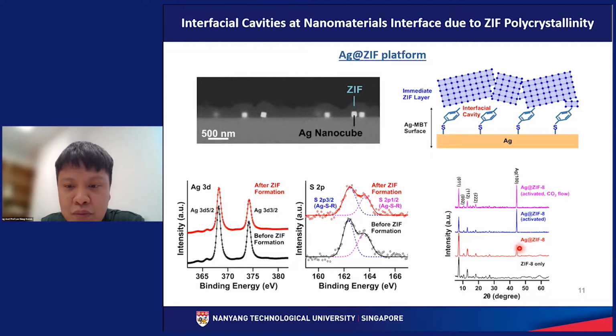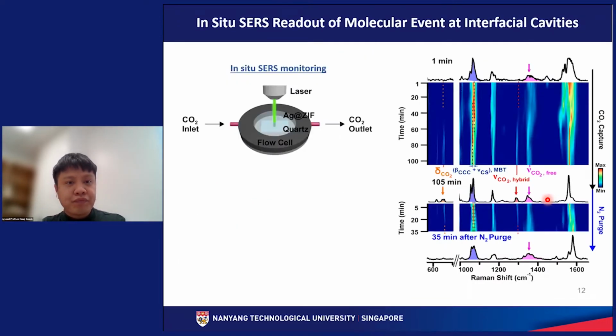Okay, so this MOF layer is very stable, whereby we can activate them under vacuum and high temperature of 120 degrees Celsius, and they can still be around and be stable throughout the entire reaction process. So after which we begin to in situ read out the molecular events at the interfacial cavities using surface enhanced Raman scattering. So in this example, we use in situ SERS monitoring.